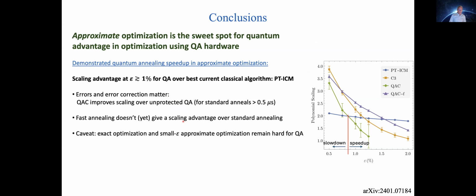So I hope to have conveyed here that approximate optimization is the sweet spot for a quantum advantage in optimization using quantum annealing hardware. A decade of trying to do this with exact optimization didn't work, but with approximate optimization, it finally worked. As in the sense that we now have demonstrations of quantum annealing speedup in terms of scaling. And the scaling advantage occurs roughly at optimality gaps of about 1%, not at 0, which would have been exact optimization, but 1% for quantum annealing using D-Wave hardware over the best current classical algorithm, PT-ICM.